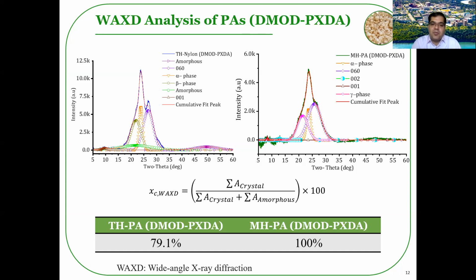The apparent degree of the polyamides' crystallinity was calculated using this formula, by dividing the area under the peak of the crystalline phases by the total area under the peak of both crystalline phases and the amorphous phases, multiplied by 100. Fortunately, microwave irradiation promoted the crystallinity of the semi-aromatic polyamides to 100%, while the semi-aromatic polyamides treated under the traditional heating process had about 79% crystallinity.